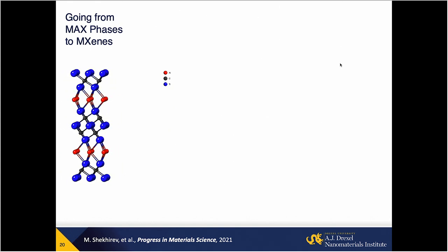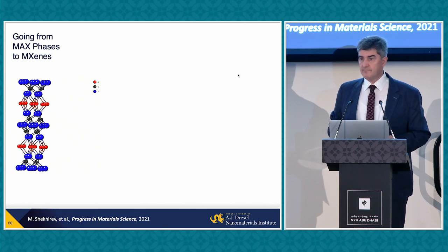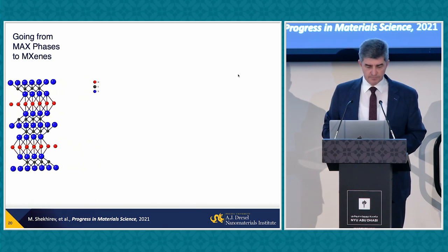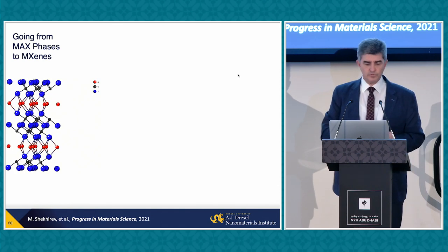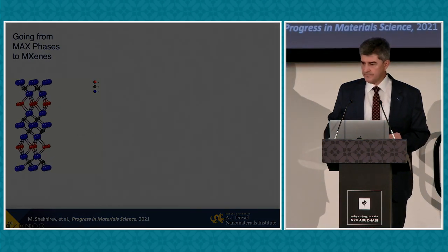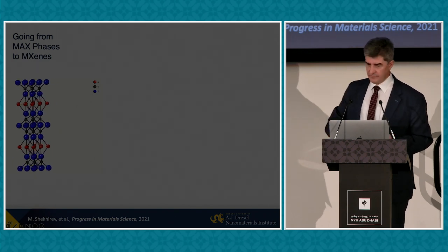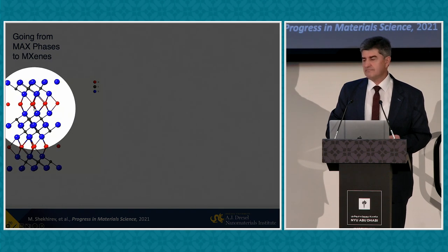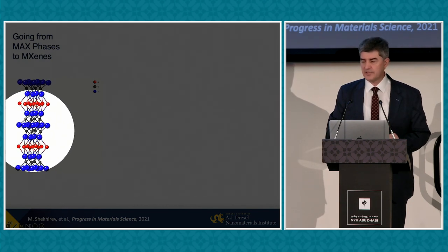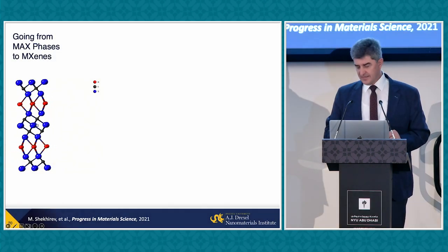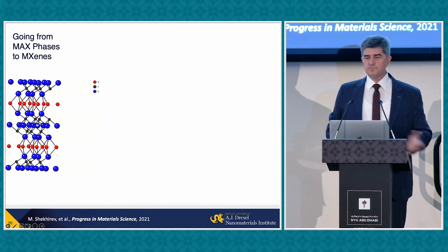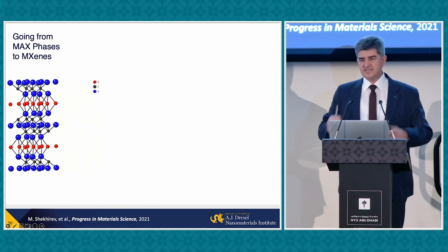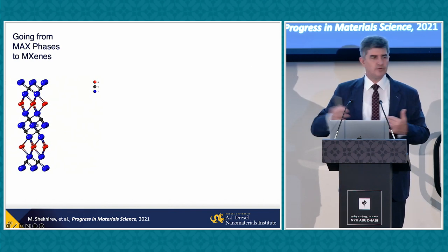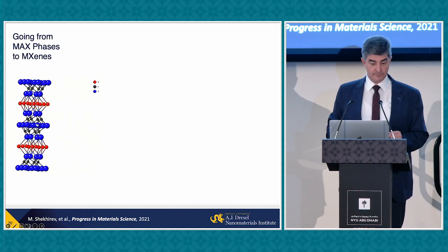Moreover, when I came to Drexel University, I interacted with my colleague, Professor Michel Barsoum, who is known as the father of so-called MAX phases, structures you actually see here. I lost my pointer somewhere, it went away. Which consists of these red layers of aluminum or silicon atoms, and the blue ones are those MX layers, carbides and nitrides. And I asked Michel, can we exfoliate them or make nanotubes out of them? He told me, no, impossible. They have strong covalent and ionic bonds between these layers. You cannot break them down.